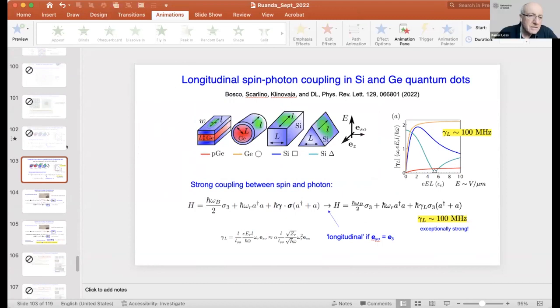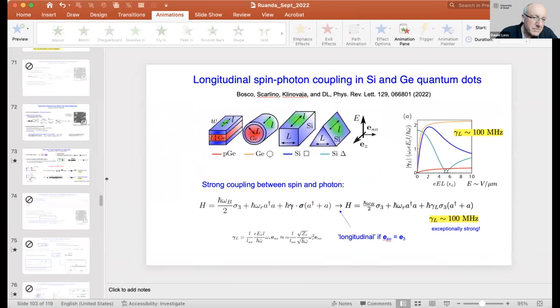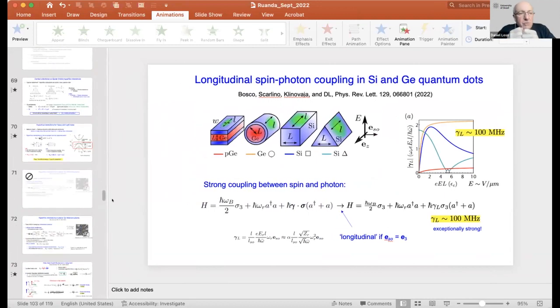So in this structure, there are two materials coming together, let's say silicon and germanium, and they have different lattice constants. And when they match, there will be a stretch or a compression. And this will then cause strain, and this strain will be relaxed as you go away from the interface. And that will have an effect in the end, which is similar to a spin-orbit interaction. And then this can then affect the strength of the spin-orbit interaction and the coherence properties of the system.